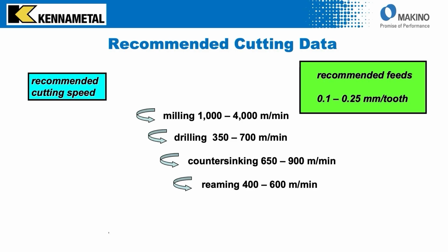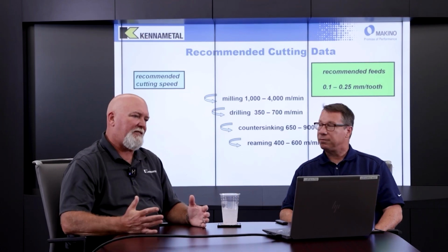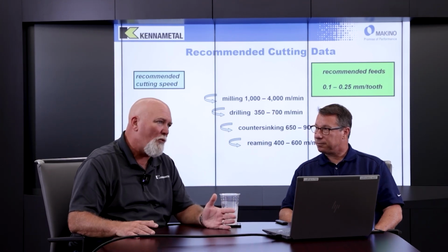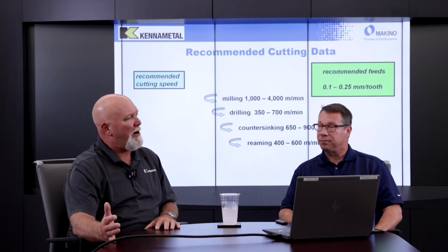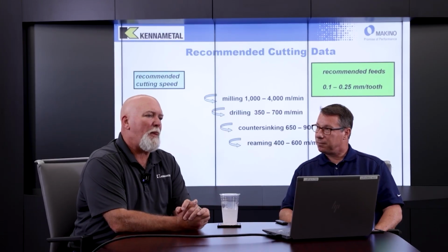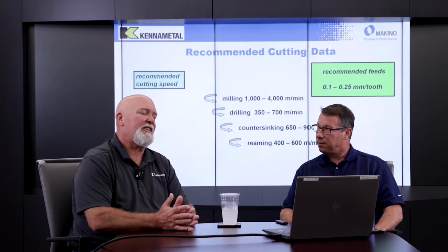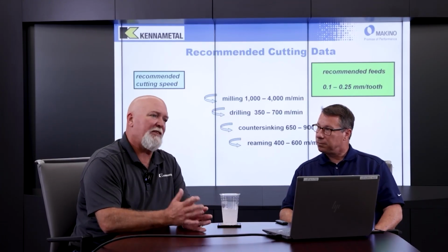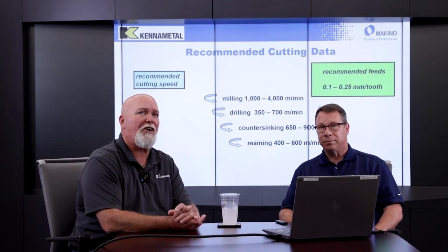From a feed rate standpoint, how does that pertain to this discussion? Yeah, and again, it's by application to some degree. These are general parameters, but from about 0.1 per tooth up to about 0.25 a tooth is where we like to run these. And for me, particularly on the milling side, I'm a feed it kind of guy. I'm also a time-in-cut guy, that tool life on and on.